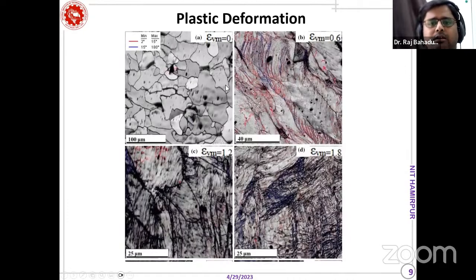So let us come to the results of the plastic deformation. This is the microstructure of low carbon steel, which has carbon of 0.08%, very less carbon, and it has very little strength also. In that microstructure, it's basically an EBSD micrograph, electron backscatter diffraction; by this technique we have taken the image. This is the undeformed material first, and the second one is deformed through equal channel angular pressing.